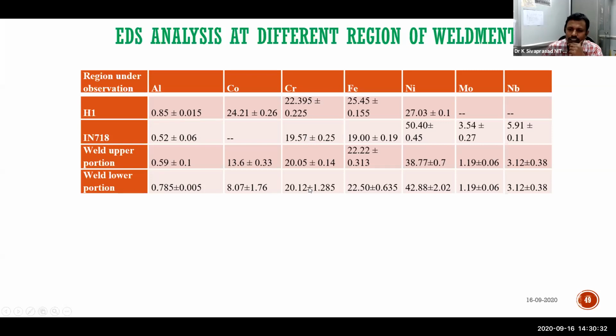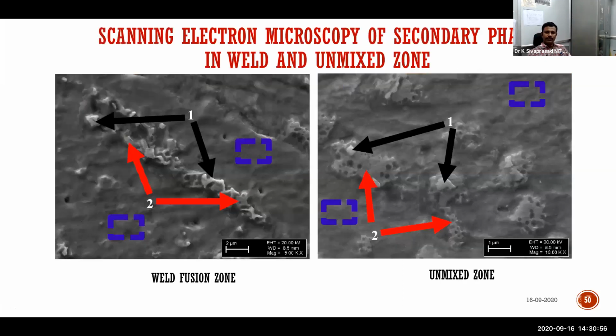Chromium is of comparable value because chromium is there on this side and also on that side. Similarly, iron and nickel. In fact, in the fusion zone nickel is higher because Inconel 718 is contributing a good amount of nickel. It's a nickel-based alloy, with higher nickel compared to the high entropy alloy. So this will favor the formation of a single phase FCC structure compared to other things, except these Laves phases.